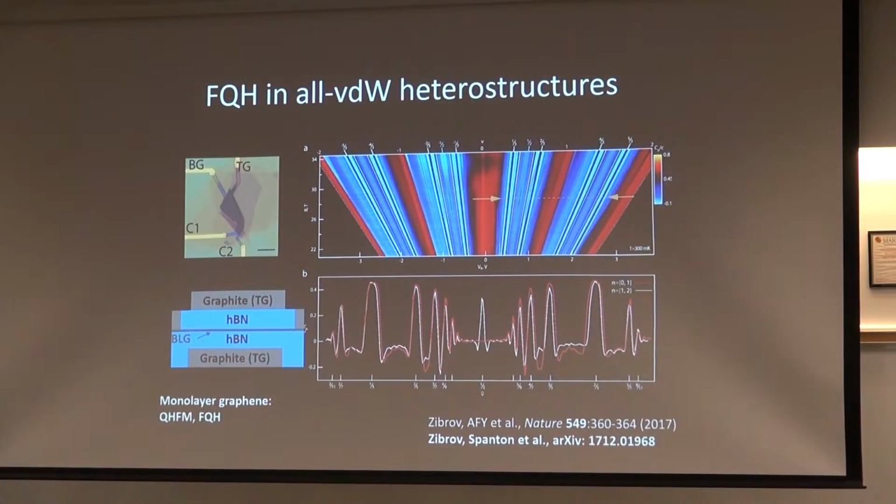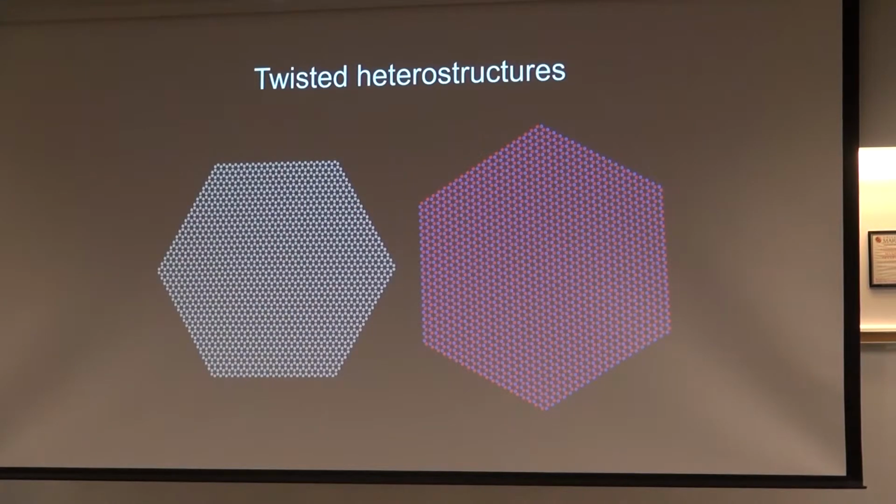What are the sizes? I'm interested in the distances. Yeah, we try to make this relatively thick so that we don't screen any interactions. That means for us something like 40 or 50 nanometers thickness of the hexagonal boron nitride, sometimes a little bit more. Certainly, if you start to make them thinner, you start to see changes. We don't understand it quantitatively, and we haven't done it systematically.